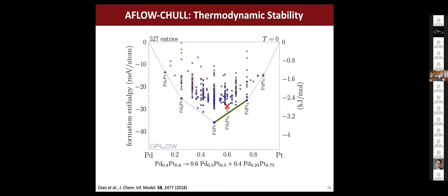So you can see that the decomposition reaction is entirely given by this picture. Here we have our Pd2Pt3 mixture, and it's going to phase separate. The decomposition reaction is dictated by these two components here. For any given unstable compound, we take our eyes from that compound and drop them straight down to the tie line directly below it. That dictates what the decomposition reaction is, and the coefficients are dictated by chemistry, just balancing out the relative amounts of each component.